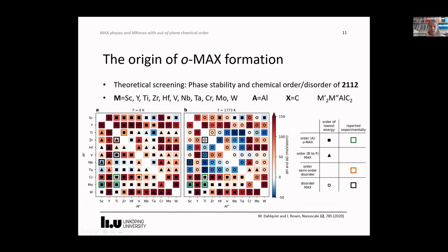We have scandium with niobium, tantalum, and tungsten, and we have tungsten scandium and tungsten titanium. Another important observation is that the number of stable phases increases when we go from here to here. This is thanks to a large number of predicted new disordered phases represented by these circles. No squares means a lot of materials that remain to be realized. And interesting to note is also that, for example, niobium phases here, where niobium is actually not found in the ternary MAX, but they are stable with niobium as the majority M element.